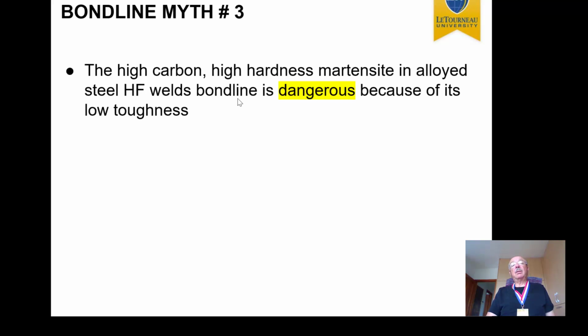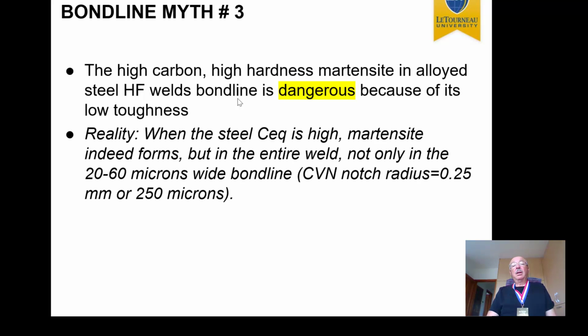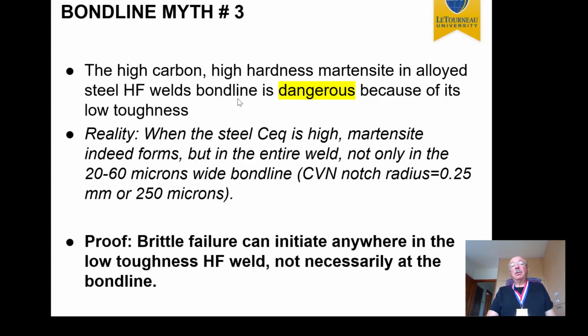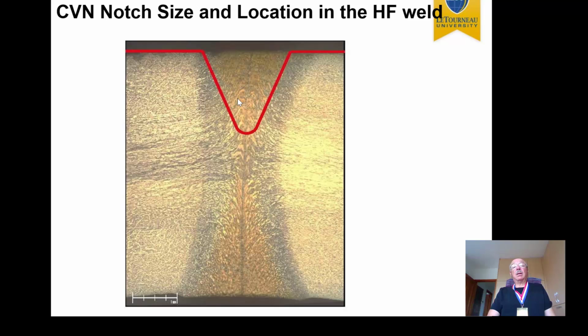And the final myth that I wanted to bring to your attention is that because sometimes high hardness in alloy steel is found there, people concluded that bond lines are dangerous because they can have low toughness. Well, in reality, the entire weld has poor toughness at this stage. For instance, if the bond line is 20 to 60 microns wide, where are you going to put the notch? Because brittle failures can initiate anywhere, not necessarily at the bond line. And here's an example. The typical notch of a Charpy specimen is 0.25 millimeters, way bigger than the bond line. And then what happens if somebody doesn't place the notch right there or here, the result should be the same.